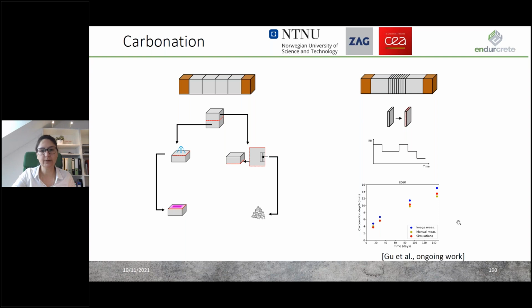You see that here on the bottom of the slide, where in red you see the modeling results, and in blue and in yellow you see our experimental results of the carbonation depth, either determined manually by measuring them with a ruler or by image analysis. So in a nutshell, this effort, by taking actually all the parameters we had as possible answers before into account, made us able to set up a really good model and confirm that with some experimental data on top. I have to say that this model also works for various cement compositions. So this is the result of the EnDurCrete binder, but of course we tested that also on our references.